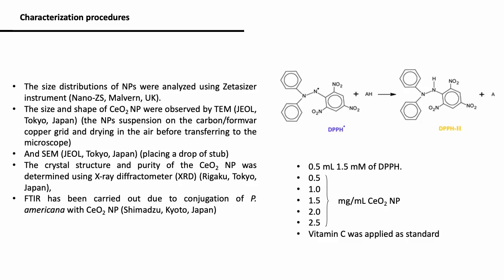The synthesized cerium oxide nanoparticles were characterized using a particle size analyzer and zeta potential, transmission electron microscope, scanning electron microscope, XRD, and FTIR analysis. In brief, the size distributions of nanoparticles were analyzed using Zetasizer instruments. The size and shape of nanoparticles were observed by transmission electron microscope and scanning electron microscope. The crystal structure and purity of the nanoparticles were determined using XRD. FTIR was carried out due to conjugation of Persea americana with cerium oxide nanoparticles.